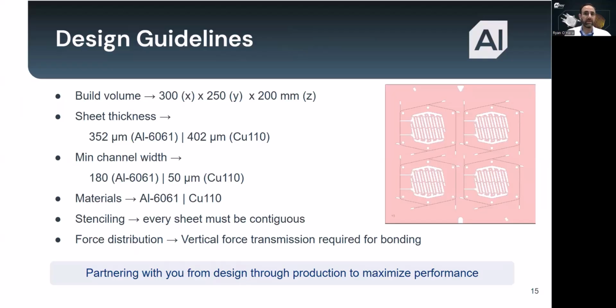Sheet thickness is another key parameter. For aluminum 6061, we're at 352 microns, and copper 110 at 402 microns. That thickness defines the layer resolution of the process and the scale at which we can create internal features. These thicknesses have been chosen to maximize process efficiency while delivering the resolution needed to meet most thermal performance requirements.